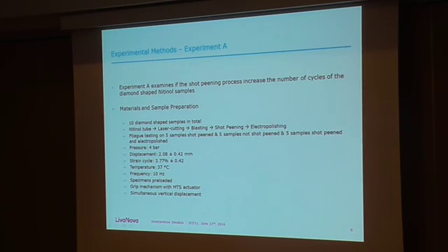We have divided this whole experiment into two sub-experiments. The first experiment is simply to see if the shot peening process increases the fatigue resistance of these diamond-shaped samples. And experiment B is to see if there is an increase of fatigue resistance, how to achieve this maximum fatigue resistance at the lowest shot peening durations because we cannot peen forever. For the experiment A, we've prepared 10 diamond-shaped samples in total. These were coming from the raw material from a nitinol tube. They are also electro-polished.